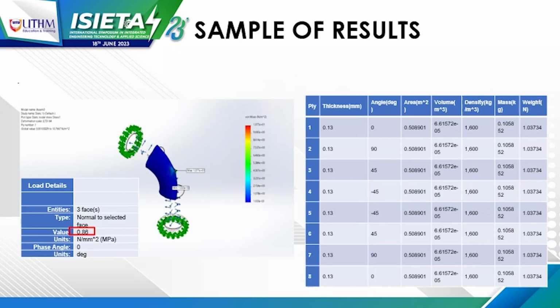This is a sample of the result we got from our SolidWorks simulation. This is for the 0, 90, 45, and 90, 45 degree lamination orientation with 0.13 mm thickness, 8 plies. We can see the load of 0.86 megapascal was applied, and the maximum stress is 10.77 megapascal. This is a sample result, and this will be generated for each and every lamination orientation for the 4 different types of loads applied.